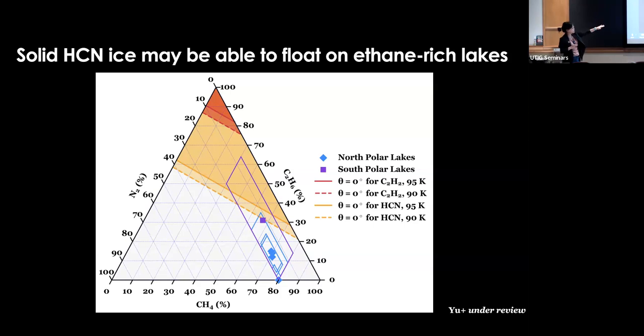But it looks like solid HCN, which is totally not healthy, may have some non-zero contact angle areas that do overlap with measured lake composition. So our conclusion is maybe it's able to float on ethane-rich lakes, okay? But the thing is, there's actually only one lake with that composition that's overlapping with that non-zero contact area, and it's a lake in the South Pole. Most of the lakes on Titan are in the North Pole, and this is where we see all the magic islands and stuff like that. There's no overlap at all.